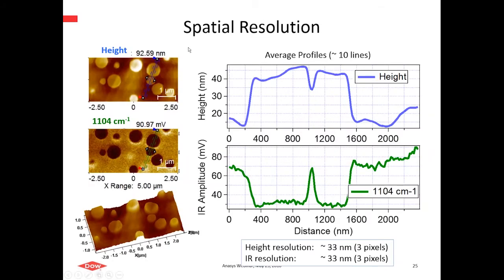And then finally, let's look at spatial resolution, kind of revisit that question. We have a case in this morphology where we have both two rigid domains in very close proximity, so we can do some average profiling across this region of the image, both in height and then in the IR response, and make estimates again from these step edges in terms of spatial resolution. And here we're seeing about 33 nanometers resolution in this very real world system. So again, confirming what we knew already from our test samples.